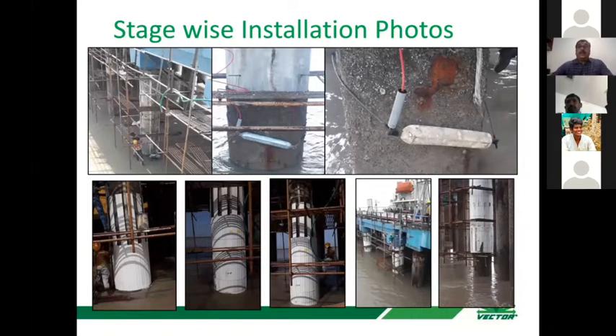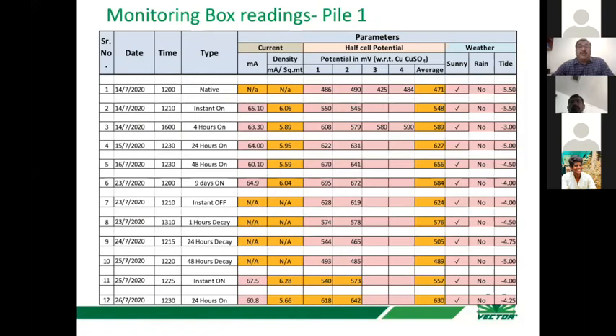And then there is a bulk anode, in the center and the right-hand side photo, and special modular jackets have been installed, which will stay in place. And then the concrete has been filled between these infills of the old column and the new jackets. So it's a simple jacketing, but with the addition of special anodes with the wicking action, a bulk anode at the bottom, which will be there in the water, and PVC modular jackets. And then you simply close everything. We are monitoring the system as of now.